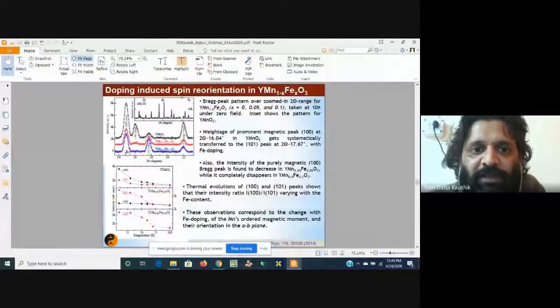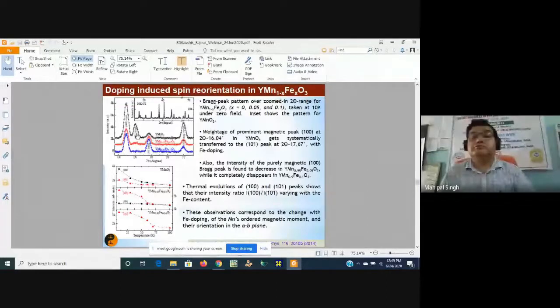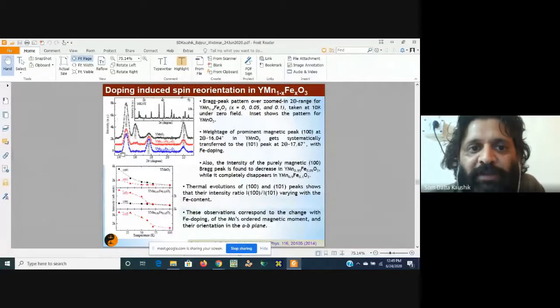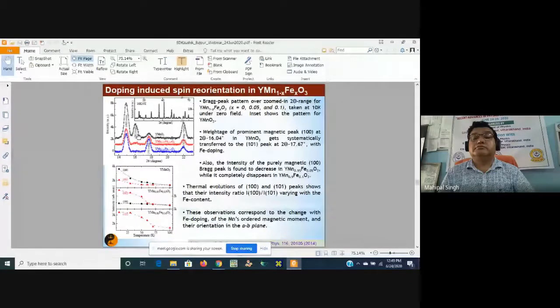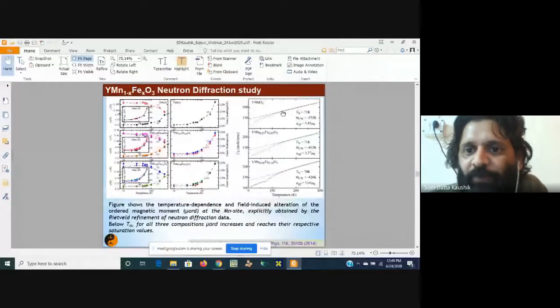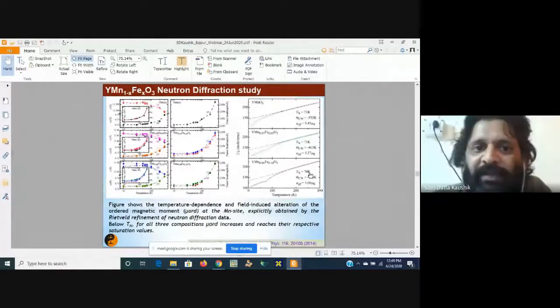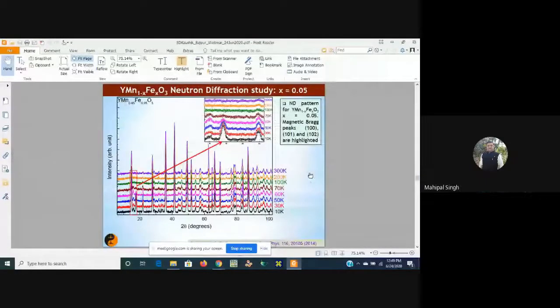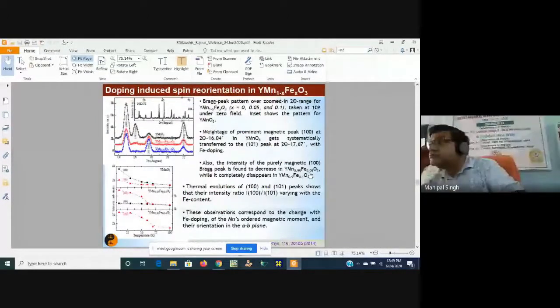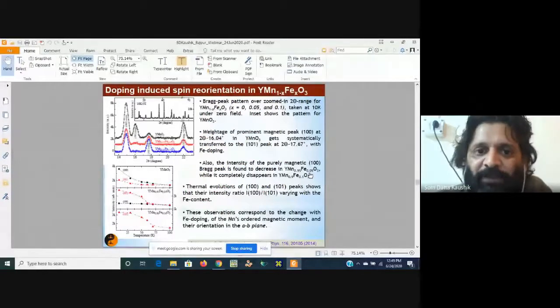So this is pure YMnO3, and this is 5% doping and 10% doping. So that is the idea: if you carry out the magnetization, for these samples the magnetization TN is more or less similar, 71 Kelvin, 71 Kelvin, 70 Kelvin. But you cannot identify what the magnetic structure looks like. By carrying out the neutron diffraction, you can see that there is a change in the magnetic structure. The structure is changing, and this can be identified using neutrons.